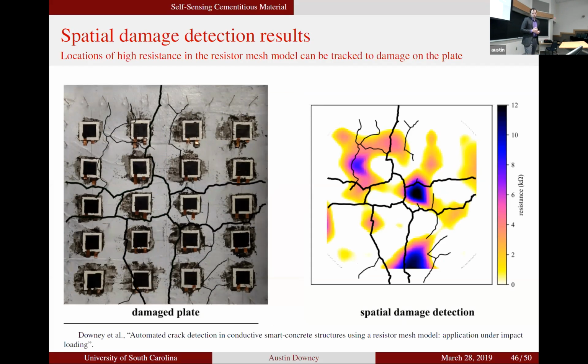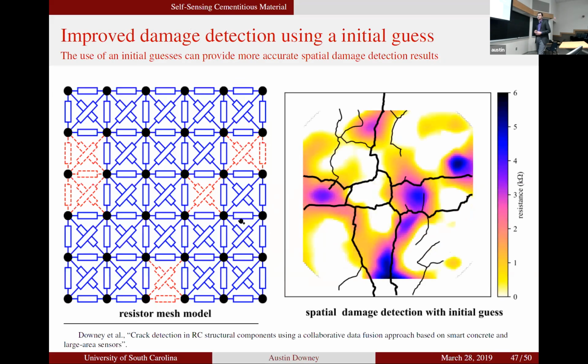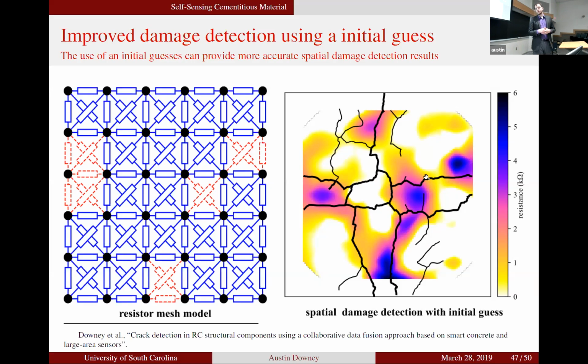However, like any machine learning algorithm, if we provide it with a better initial guess, we can get better results. So here's those exact same results, just in a different color map and flipped to look from the back. These were the SECs that we discussed before on the back of the plate. And so 20 SECs. From the SECs, we were able to see individual cracks that form through particular SECs. When we take a crack that forms through an SEC and feed it into the algorithm, we get a much better result that now can start to track not only some of the spalling, but the much smaller damage that happens along the crack lines, right? And this is provided by the fact that the initial guess means we're not just concentrating on the largest damage first, right? We're spreading out to where we know some more damage is.